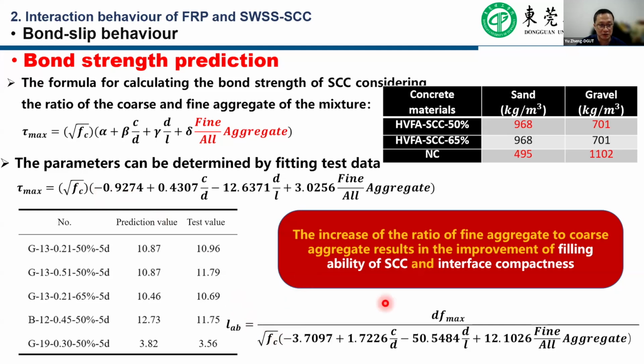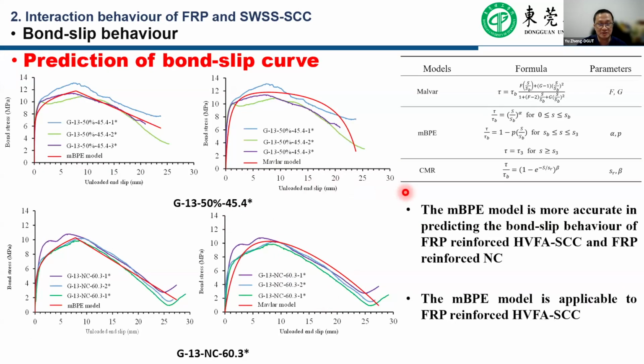And furthermore, we can use that to predict the development length to use the FRP and self-compacting concrete in the future. We use the current prediction method for the bond-slip curves. We can find that the mBPE model shows accurate results to predict the bond-slip behavior for the self-compacting concrete and the FRP reinforced structures.